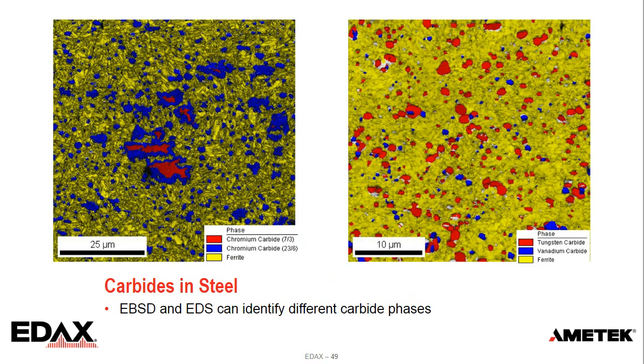This is just an example of looking at different carbides in steel. So on the left here, these are looking at different MC carbides, where M is chromium in this case. So we're looking at a 7-3 carbide and a 23 carbide, the blue one. And you can see how they're distributed. They have a very interesting structure. Some of the carbides have sort of an interior-exterior carbide distribution. On the right, this is looking at tungsten carbide, vanadium carbide in a ferritic matrix. We can see where they're present.